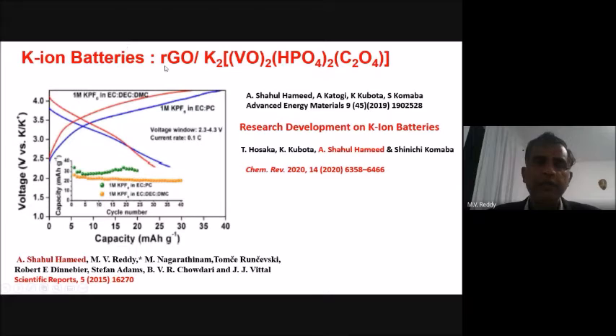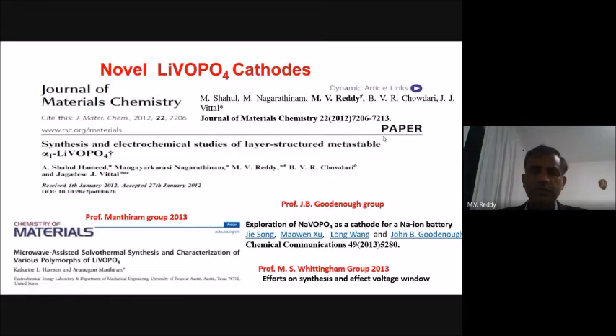So sometimes people may ask, we also work on sodium. From our experience, lithium is good, followed by sodium. If we talk about potassium batteries, we get a lower discharge. You know that the potassium ion has a slightly higher ionic radius, which causes mobility issues. Anyway, recently with a small improvement in the electrolyte combination, people have achieved improvement in the capacity. These are a few examples of novel vanadium materials, for example, lithium vanadium fluorophosphate type materials.